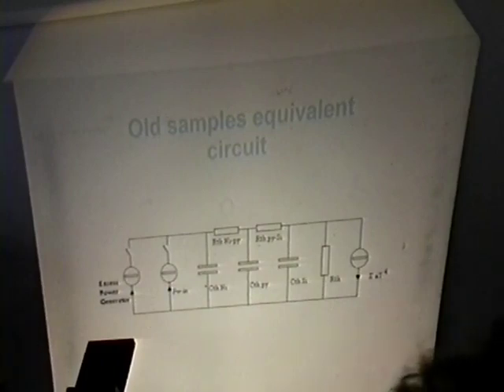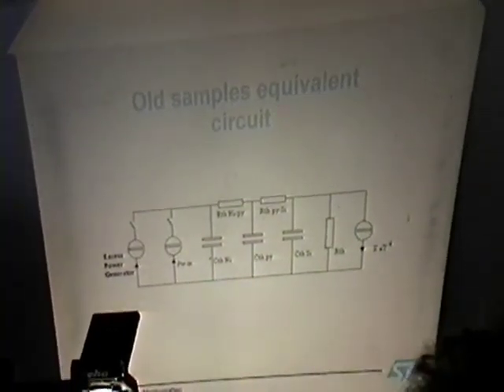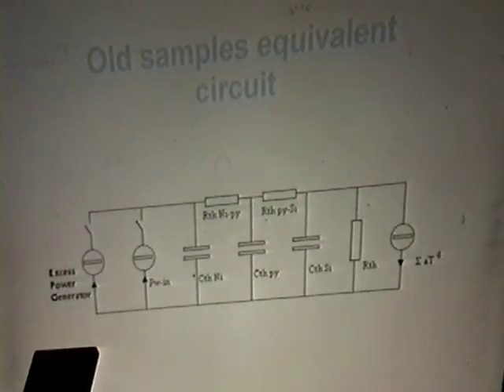The old samples that I showed you have this kind of electrical equivalent circuit. To simulate what happens inside the sample, we can translate the thermal parameters into electrical parameters and simulate if this circuitry matches the experimental results. We have the excess power generator, because at high temperature we need to take into account also the energy lost by the emission